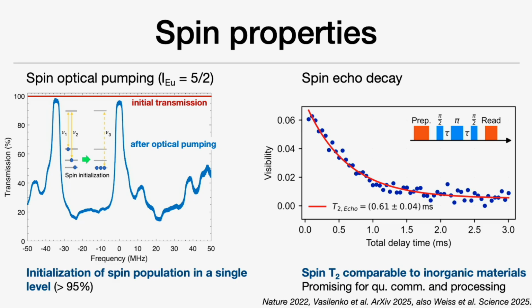And very recently, in collaboration with colleagues in Germany at KIT, they were able to measure spin echo decay, so the quantum state lifetime of the spin transition. And here they found about 600 microseconds, which is very nice because it's comparable to a few inorganic materials, traditional crystals. So we are not very far from what we can see in these more traditional materials, and this is also making the whole system very promising for applications.